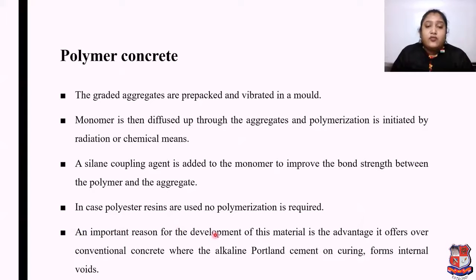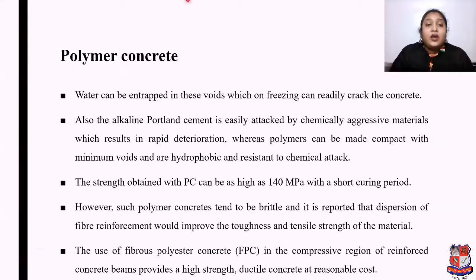An important reason for the development of this material is the advantage it offers over conventional concrete, where the alkaline Portland cement on curing forms internal voids. Water can be entrapped in these voids, which on freezing can readily crack the concrete. Also, the alkaline Portland cement is easily attacked by chemically aggressive materials, which results in rapid deterioration, whereas polymer can be made compact with minimum void and is hydrophobic and resistant to chemical attack.